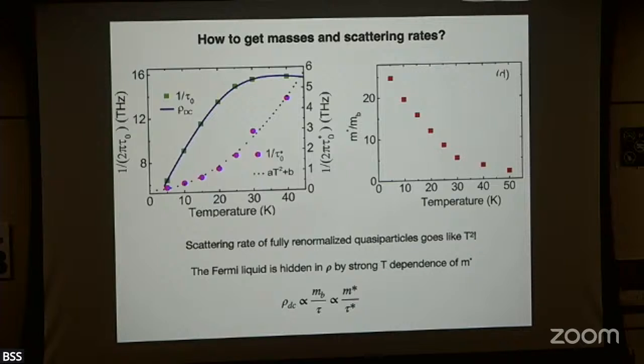I would say no, there's no evidence for that, because you might have put credence in the fact that there was linear T resistivity despite the fact there were multiple bands. But we can show that there is this scattering rate that, as I write here, has physical significance because it's really the rate at which current relaxes, which is a macroscopic quantity.